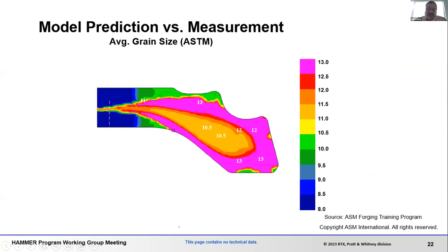Here's a really interesting example of a part that was produced with a mechanical press. The input material is actually a 718 material. It was heated up to a temperature and nominally had ASTM 8 grain size, 50 microns, something like that, maybe. I forget the number exactly, something on that order. So it's relatively coarse grain size. As that material has been deformed, it starts to strain and recrystallize, and it will recrystallize dynamically and start producing grain sizes of ASTM 12 and 13, which are something on the order of like 8 microns or so.